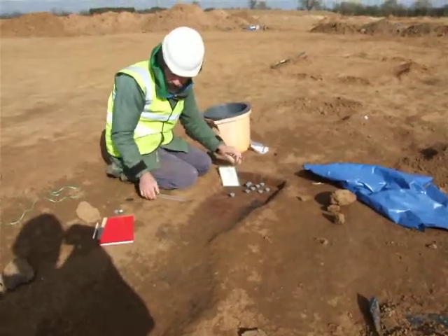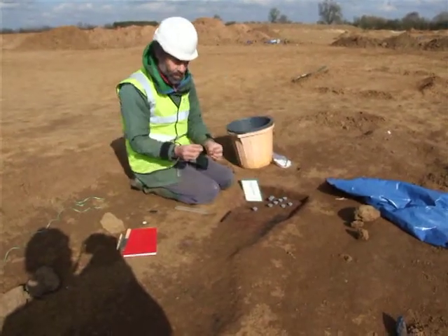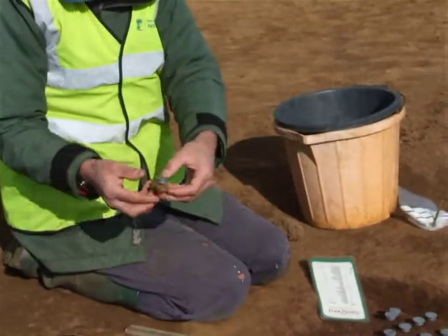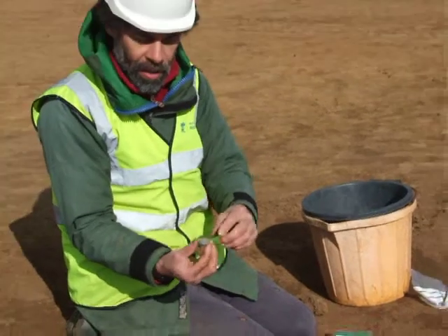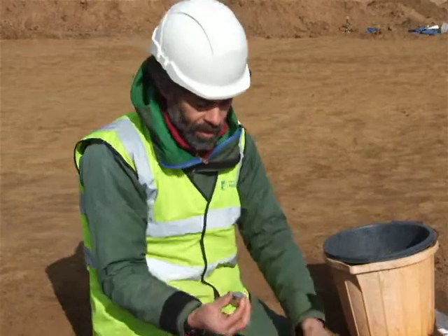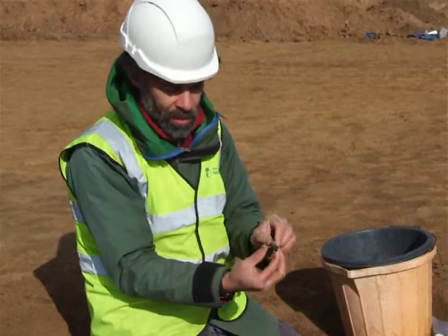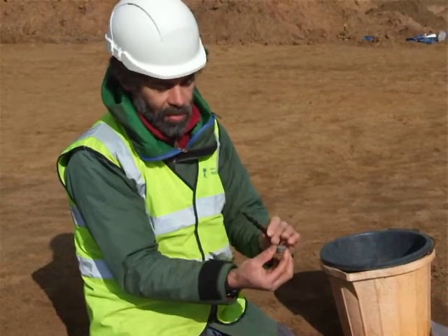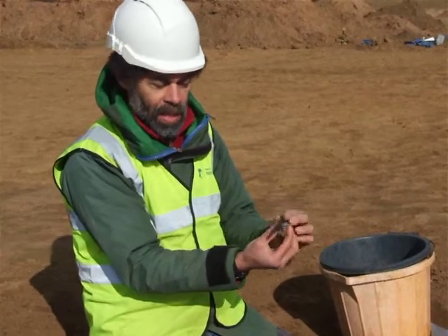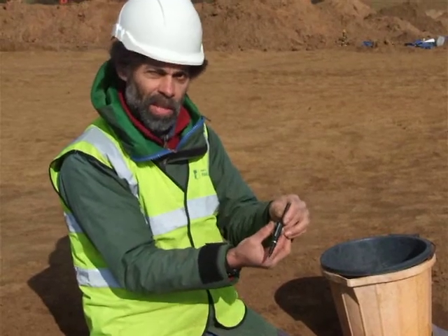When I've done that for all of the samples, I'll remove the buttons, cut them away, and I'll find a piece of kiln about that size stuck onto the bottom of the button. It then goes into the laboratory, where I dry and consolidate the material, and each sample goes into a magnetometer that measures the direction of magnetism in the burnt clay relative to the arrow pointing towards the sun, and relative to this surface. The computer attached to the magnetometer then gives me the declination — that's the horizontal bearing of the magnetization — and the inclination, the dip of the magnetization.